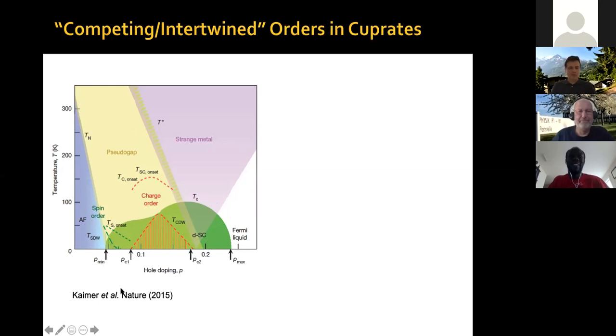As you can see, the superconducting dome is not a single dome. You can see that it's more like a camelback. It has two domes. In particular, there's this region where there is sort of an inflection point, where there is a depletion of the superconducting TC around this 1/8 doping.